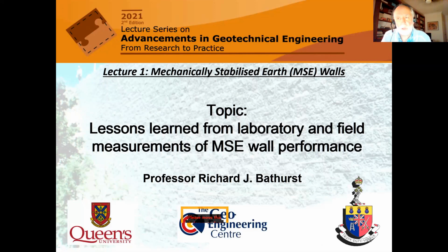And I've seen some failures in my own country, where they stretched the limit and used cohesive frictional soils with about 25% fines in them. What happened was that water got into this backfill over a period of several years, and the failure happened several years after the walls were built. It could have been prevented if they'd kept the water out. So the combination of so-called cohesive backfills and water could be a recipe for bad performance.